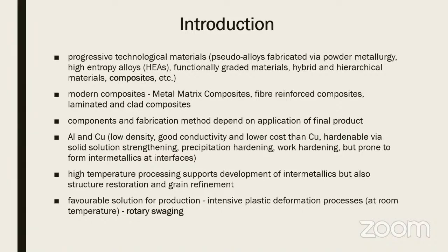I have chosen aluminum and copper. They are both very advantageous because they have, some of them, like aluminum, have low density, they have good conductivity and lower cost than copper. And they are also hardenable via solid solution strengthening or precipitation hardening, so they can be very well work hardened. However, they are prone to form intermetallic phases at the interfaces.